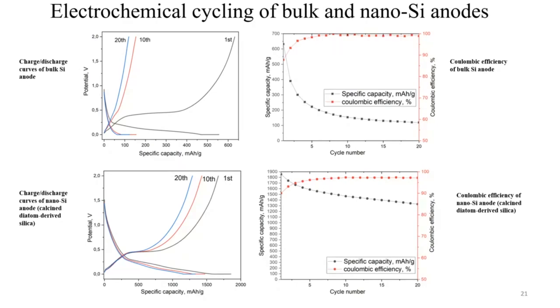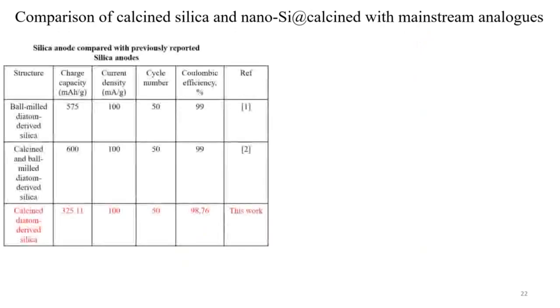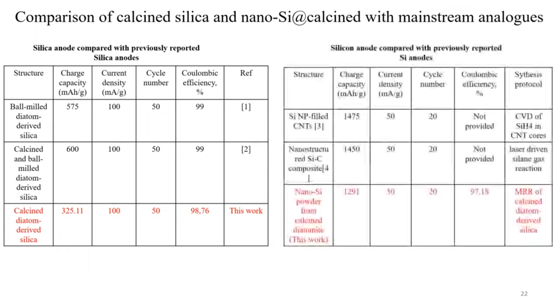And this is also seen here in the coulombic efficiency chart. A very quick comparison with mainstream analogs shows that the calcined powder offers slightly lower discharge capacity, but the ball-milled diatom-derived silica, and calcined plus ball-milled diatom-derived silica, offer much better charge-discharge capacity. And in terms of the silicon anode, compared with previously reported silica anodes, which were produced via quite non-environmentally friendly approaches, the powders produced via magnesiothermic reaction perform quite well compared with